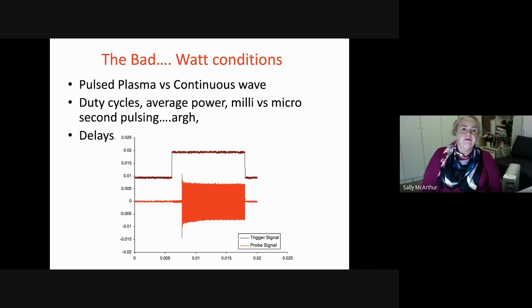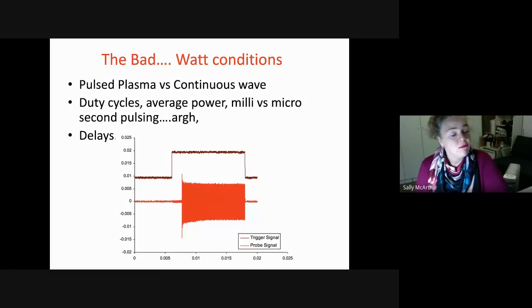So if you use just the pulse to determine what your duty cycle is or the power that you're delivering, you can have quite significant changes in the amount of power that's going into the system if you don't take these delays into consideration, particularly when you're doing millisecond and microsecond pulsing. Those delays can be a significant part of what you do. They can also be really closely affected by how quickly you're pulsing and the recovery process within the chamber as well. So this gets into your fundamental plasma physics, which I will admit right now, I am not the guru in. I am just the curious person who likes to know what's happening in terms of measurement science in our system.